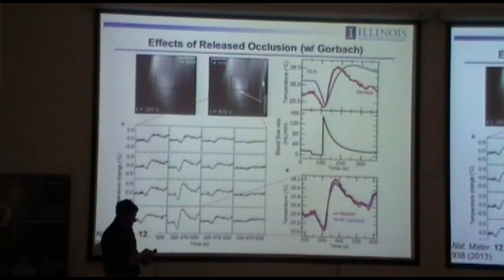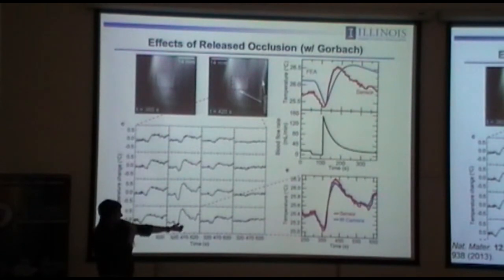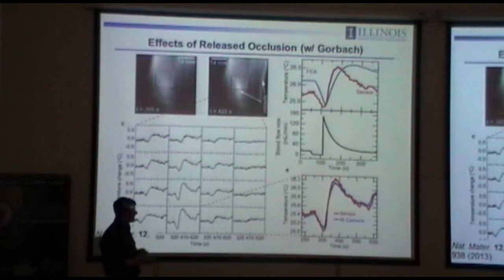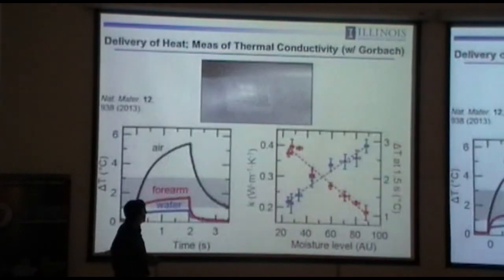You can also look at time dynamic events. So you can constrict a blood vessel, in this case the ulnar artery, and then you can release it, and you can look at temporal transients in temperature associated with blood flow through near surface arteries. And here's what it looks like. All the different channels here are sort of coincident with the ulnar artery, but only certain channels are directly spatially overlapped. And those channels have all the information. In fact, you see a downshoot, and then an overshoot, and an overdamped oscillation. And the details of that have to do with the elasticity of the arteries. So you measure arterial stiffness by doing this and then coupling it with mechanics models of blood flow through the artery.